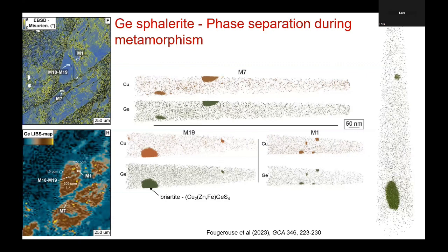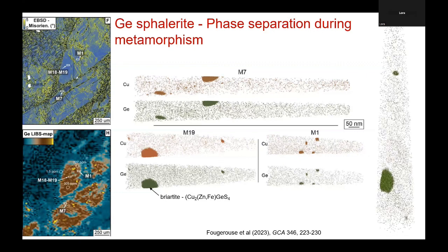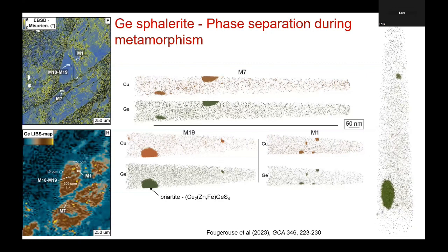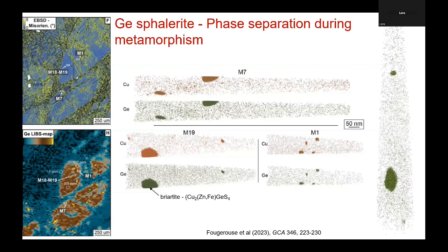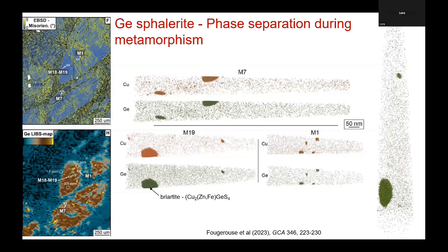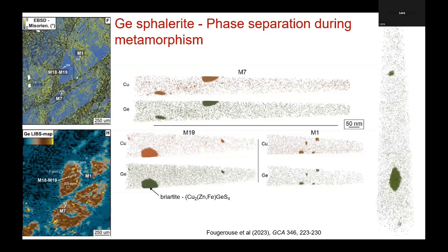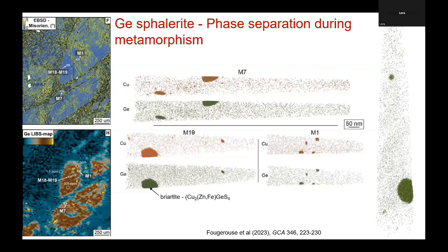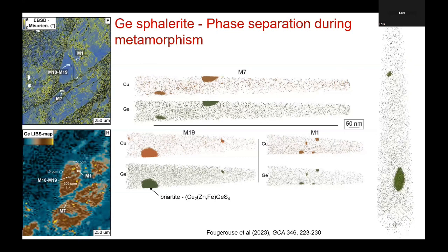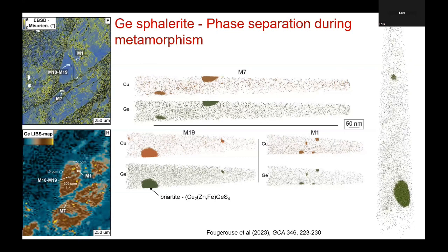Basically, dislocations cannot migrate through your crystal anymore. They get pinned by these clusters, and the rich domains of the sphalerites basically become like little islands that cannot deform anymore. So this is what you see on the electron backscatter map. These blue domains mean there is not much deformation in it, and that's where you have most of your germanium.